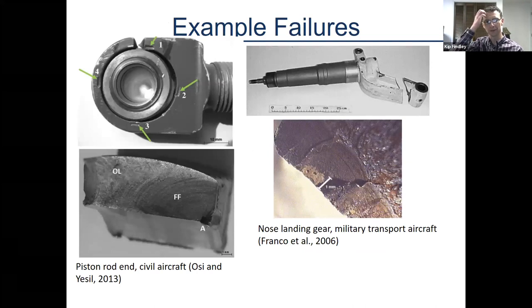So here's a couple of examples. The one on the left is from a civil aircraft. And I think this one actually failed while it was on the runway taxiing out to take off. So that's probably the best time for a landing gear to fail, before you take off, so nothing happens. But what I want to highlight is if you look at this fracture surface on the bottom left, you see this really flat region. And you see these concave marks that point back to the fracture origin. And again, these are called beach marks. And so this is a pretty good indication of fatigue. In fact, it's a very good indication of fatigue.